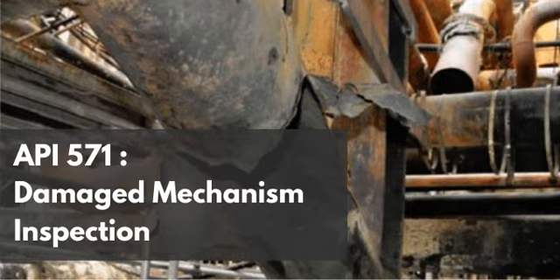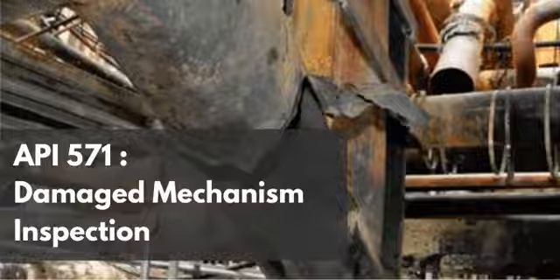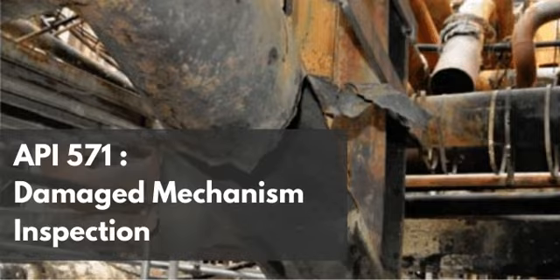But what is truly fascinating about the data here is not just what must be present to cause the damage, but what must be absent. Oh, this is a really interesting point. It highlights a strict absence requirement. For this rapid, destructive carburization to occur, the environment must have a low oxygen potential. Really? It explicitly states there must be minimal oxygen or steam present in the gas phase.